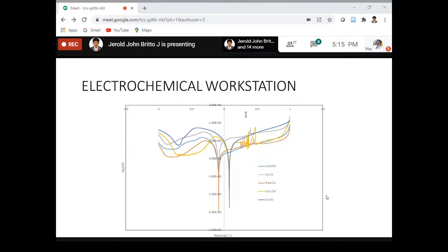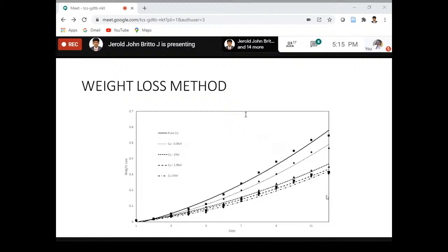In addition to this, I have also gone for the weight loss method. This is the normal method usually people do. This is actually with a 4 normality H2SO4 solution. This is the normal traditional method. We will just put a small piece of this specimen, which we have manufactured by the stir casting method, in that particular beaker.